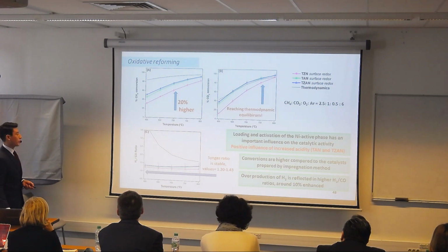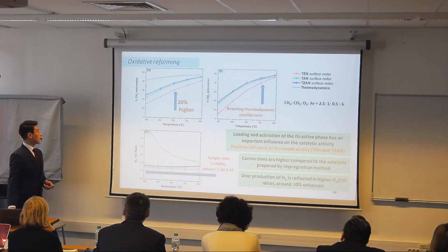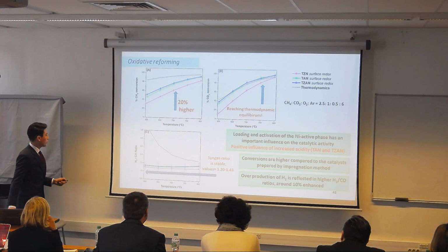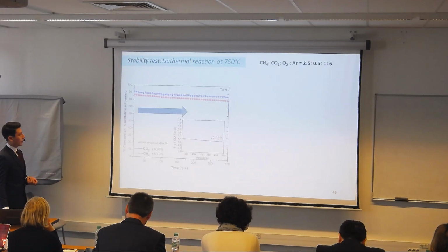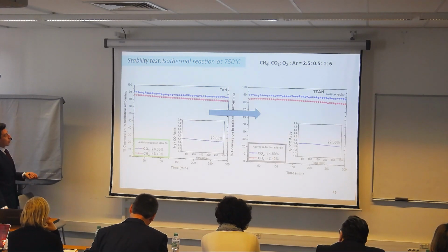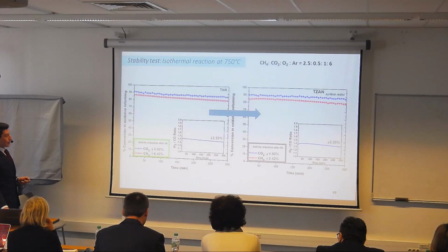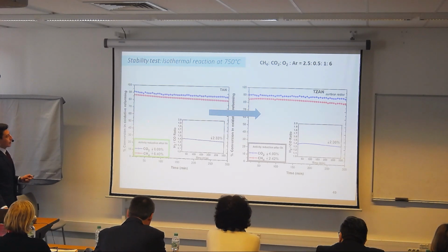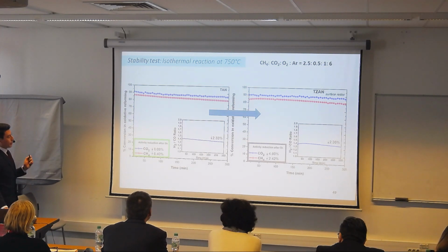As I mentioned, the production of hydrogen is reflected in the syngas ratio. We also found around a 10% increase compared to the impregnated catalyst. So here I'm showing you the stability test. In this part we have the best one from the impregnated.